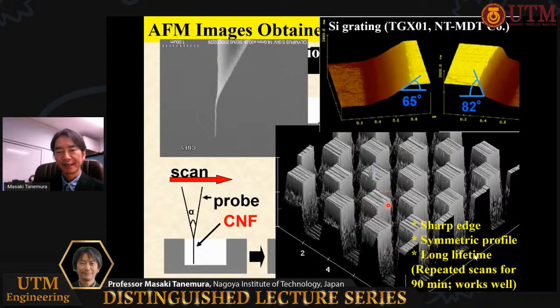You see the sharp edge and the symmetric profile. We can observe such a sharp image after repeated scans for 90 minutes. So, carbon nanofiber has a very long lifetime.